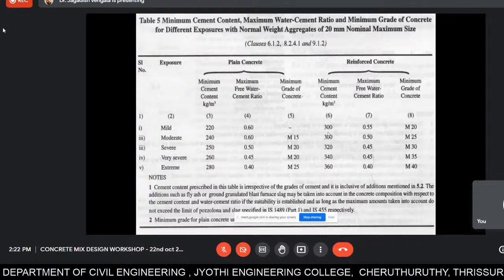So similarly, as I mentioned in the example earlier, for a normal weather condition, the structure, the columns and beams, if it is a mild exposure, then you're designing the M20 grade of concrete. When the concrete is buried under soil, you have to go for the M25 grade of concrete because it comes under moderate exposure. So mild to moderate, the minimum cement content you have to maintain is 300 kg per cubic meter, but you have to limit the water cement ratio to a maximum of 0.55 in case of mild and 0.5 in case of moderate. So what I mean to say here is exposure condition is very important. Based on exposure condition, you decide the minimum grade of concrete, and accordingly you will choose the maximum water cement ratio and minimum cement content.